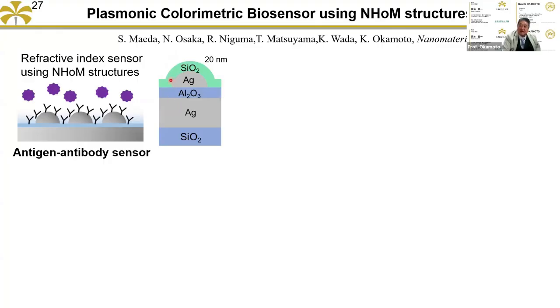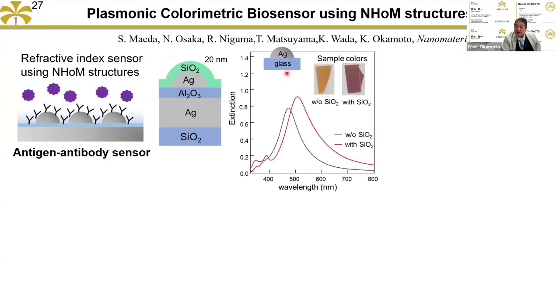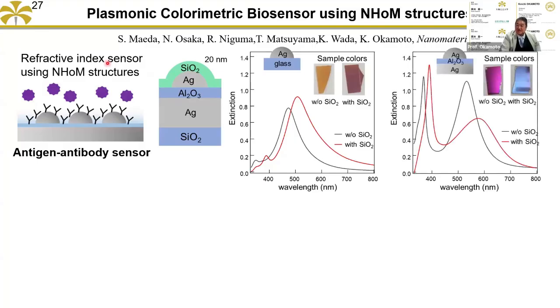So first, I just deposit silicon dioxide, 20 nanometer. That's very, very thin. That's why by naked eyes, you can see the distinction. But we deposit the silicon dioxide on the silver nanoparticle on the glass. The color is a little changed. But we put that silver substrate and the nanoparticle structure. The color is dramatically changed. The color is vivid, shocking pink and changed to sky blue. So very easily you can sense the refractive index.